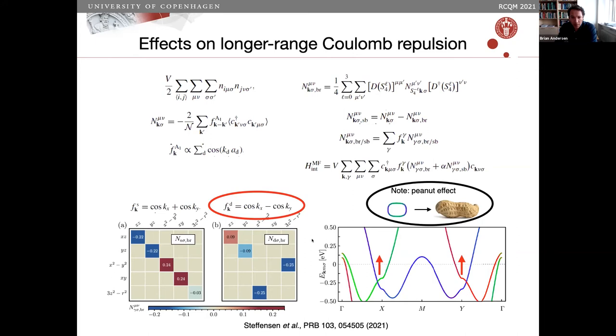By the way, this is exactly why you get peanut shapes: it's related to this factor because if you're shifting up only say the green part or the red part of these pockets, you're squeezing only along one side — that's why you immediately get peanut-shaped electron pockets.